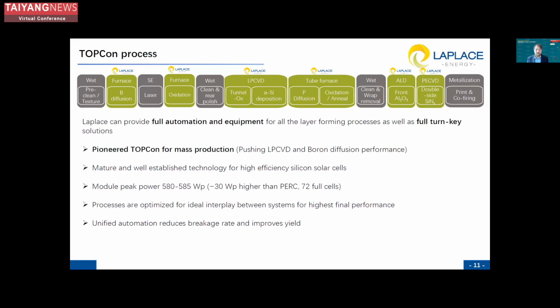Now we can say that it's a mature and well-established technology, and we can reach very high efficiencies for the silicon solar cells. We reach about 580 to 585 watt peaks, which is about 30 watt peaks higher than a PERC module when we use 72 full cell modules. I also would like to point out that our processes are optimized for an ideal interplay between all the different systems. Since we can provide the full deposition technology for the full line, we can reach the highest final performance by optimizing all this interplay. And by providing the whole automation for the full line, we can reduce the breakage rate and improve the yield.